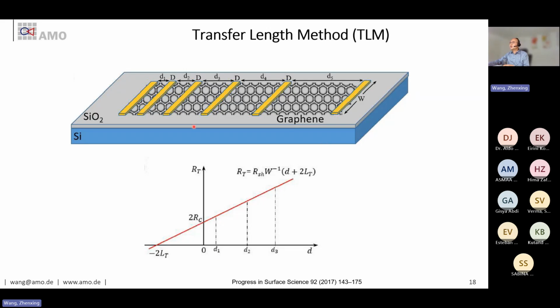So basically you make devices with different channel lengths, D1, D2, D3, and so on. Afterwards you measure the resistance of all these devices, all these channels. Then you plot them in such a plot. So this is the total resistance you measured from such a structure, and this is the distance between the two electrodes. Then you do a linear fitting, and the intercept with the y-axis is actually 2 times contact resistance, because you have contact resistance on both sides. So in the end, you divide this value by 2, then you get the contact resistance on one side.